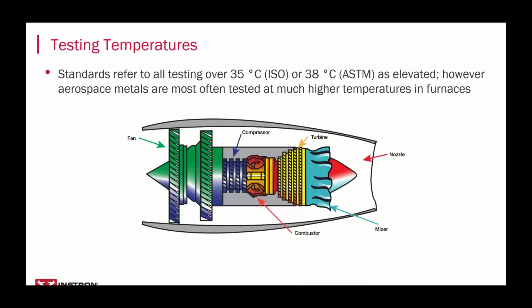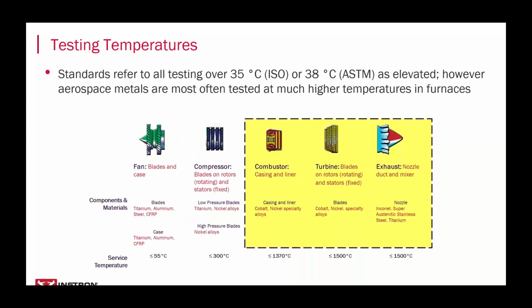Now, on the earlier slides, I noted the scope of these elevated temperature testing standards is actually anything over 35 degrees Celsius for ISO or 38 degrees Celsius for ASTM International. However, when discussing aerospace alloys, we're typically talking about metals that are tested at much higher temperatures. This is because when we look at a common application, for example, the components aft of the compressor in a jet engine, the service temperatures exceed 1,000 degrees Celsius, and the common trend in industry is increasing both the relative load and service temperature of metals in this application. This is where we really worry not only about the ability of metallic components to carry load at temperature, but also to do so with well understood minimum deflections.